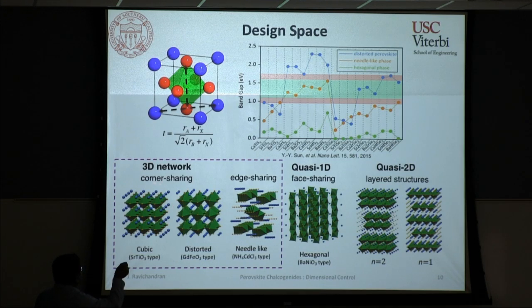So the true perovskite is defined by corner sharing of these octahedra forming a three-dimensional network. But once you have ionic sizes that do not let your system crystallize in this 3D network, you start getting this edge sharing network, which is a quasi 1D type system, which has a lot more network connectivity than a true 1D connectivity. Then you also have these hexagonal variants where you have face shared connectivity between the octahedra that gives rise to 1D chain-like behavior. So you can go from 3-dimensional all the way to 1-dimensional by just changing different elements that are present in your ABX3.